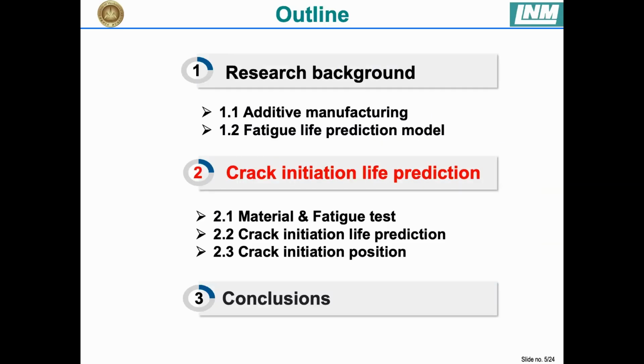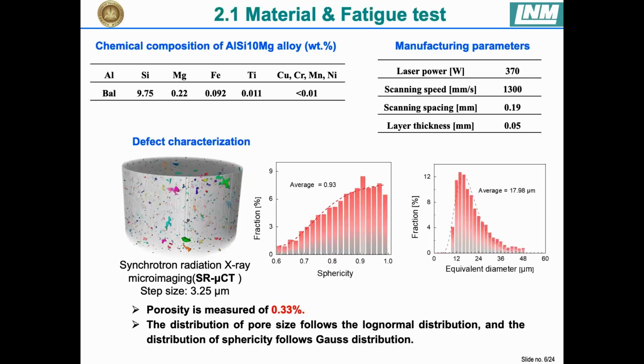Second is about the crack initiation life prediction model and the corresponding results. The investigated material in this study is AlSi10Mg, and the corresponding chemical composition and manufacturing parameters are listed here. Firstly, micro CT technology is applied to conduct the defect characterization. The porosity is measured as 0.33 percent, and the pore equivalent diameter and the sphericity follow the log normal and the Gauss normal distribution respectively.